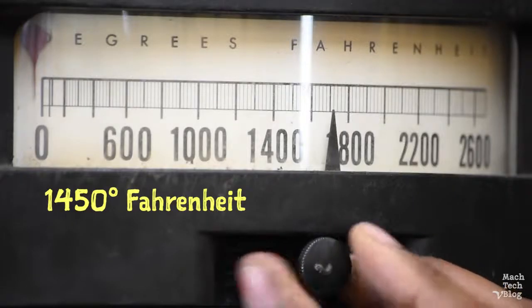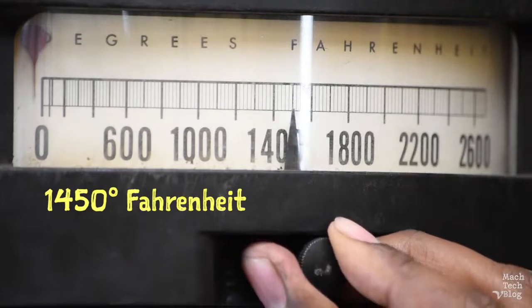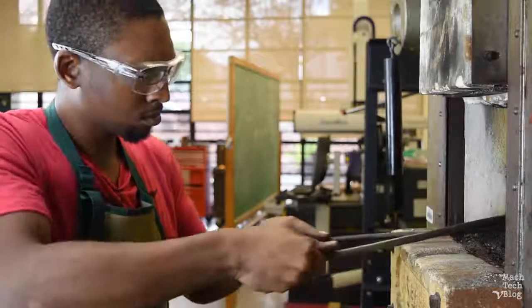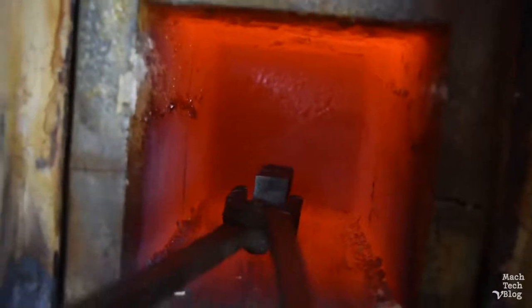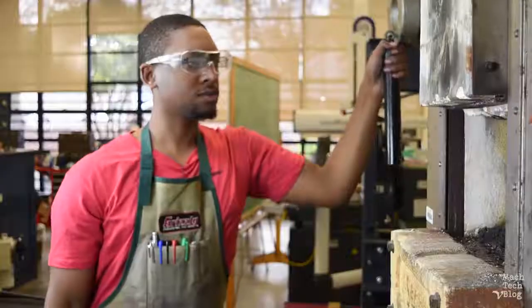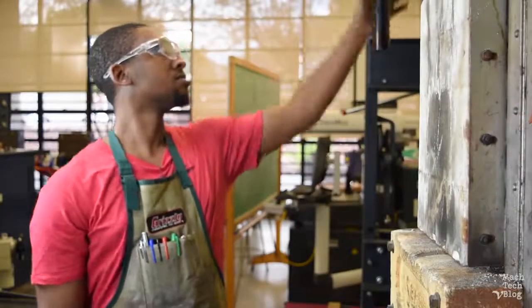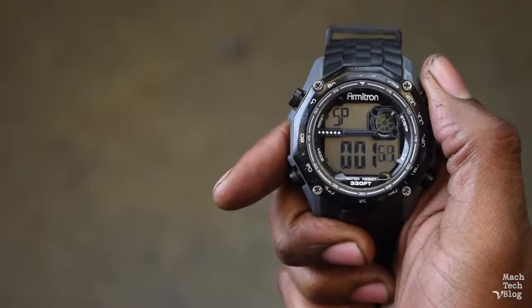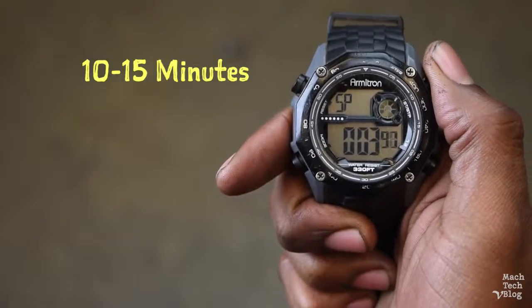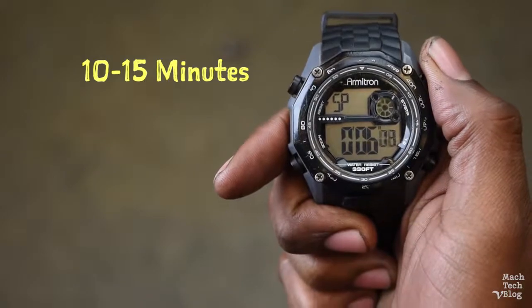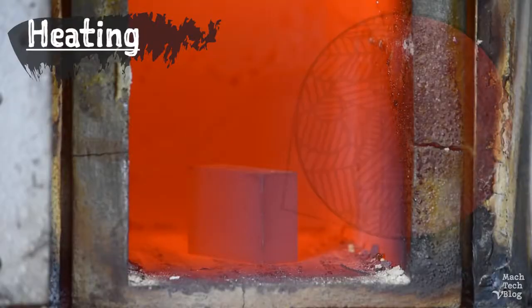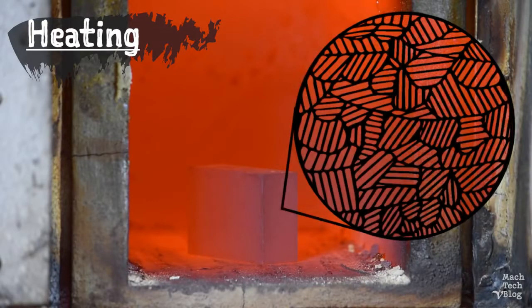Turn the heat up to 1450 degrees Fahrenheit, and then put the parts back into the furnace. We only need to get the parts up to temperature, so 10 to 15 minutes should do the trick. At room temperature, the microscopic structure of the high-carbon steel is composed of alternating layers of iron and brittle iron carbide. This microstructure is known as pearlite.